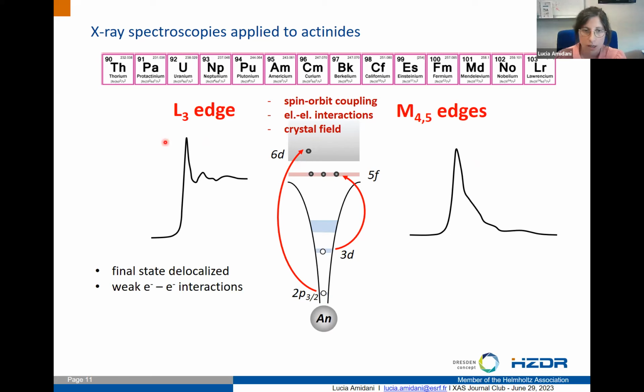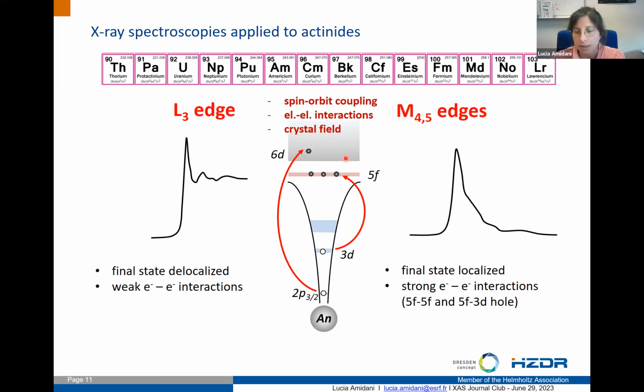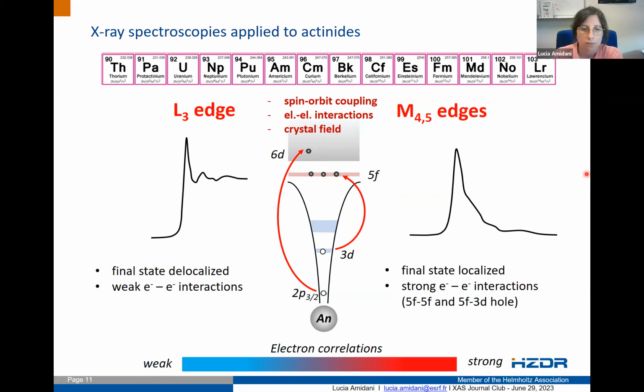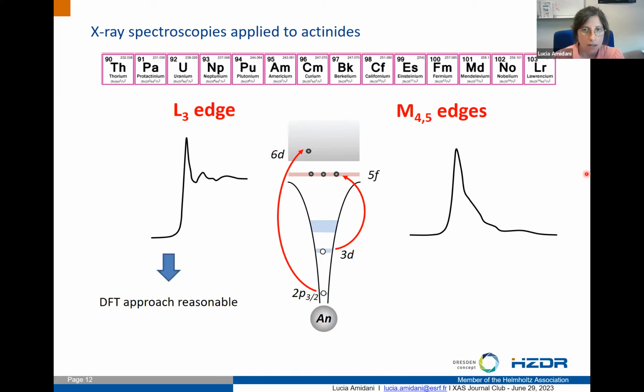If we stay at the L3 edge, the final state is delocalized, so we can say the electron-electron interactions are weak, and we stay in a certain framework. If we go to the M edges, we go directly to the 5F shell, so we have a final state which is more localized, with strong electron-electron interaction—not only between the 5F electrons but also with the core hole. This means there's a certain range of relevance of electronic correlation, which changes the approach we use for simulations. In the case of the L3 edge, the DFT approach is reasonable, because electron-electron interactions are considered only partially, but this is a safe case.